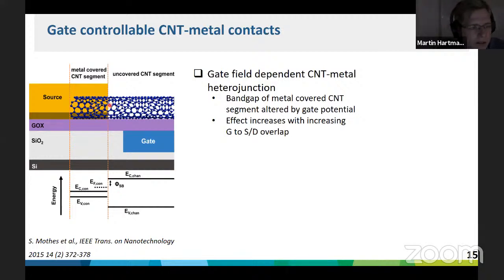The CNT metal contact is quite a complex thing, because when you have a specific metal on the CNTs, the metal can alter the band gap of the CNT. Comparing a metal uncovered, pristine CNT with the band gap of a metal covered CNT, you see that it can be changed, okay? The amount of change can be manipulated by the gate potential. The closer you bring the gate electrode to the source, the bigger is the impact of the gate field on the entire contact region. This means you can alter the contact, or the Schottky barrier at the interface between the metal covered and metal uncovered CNT region. This alteration is gate-source voltage dependent, and this can further reduce your transconductance. So this is one possible explanation.